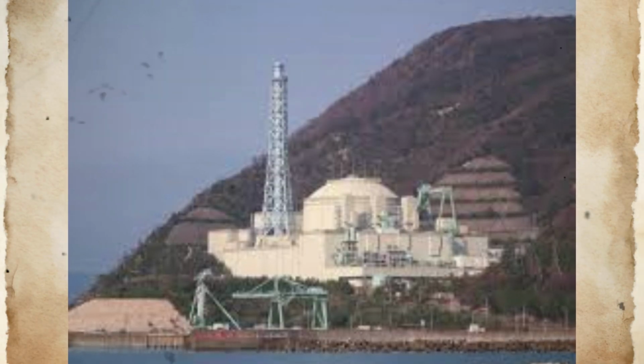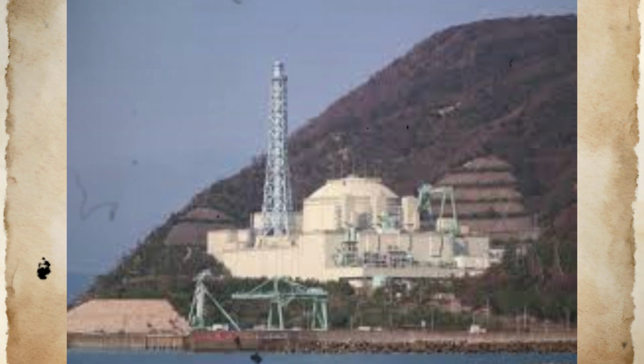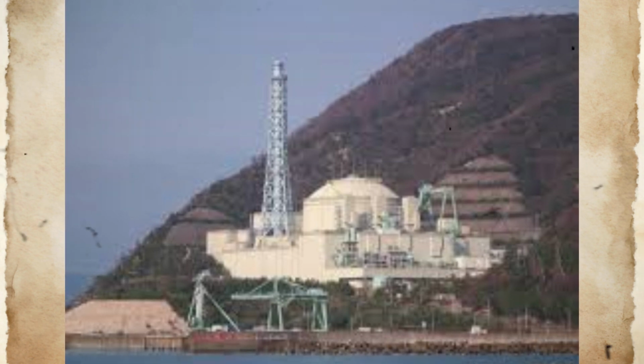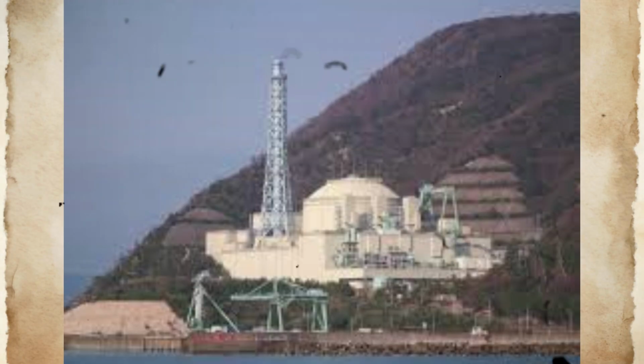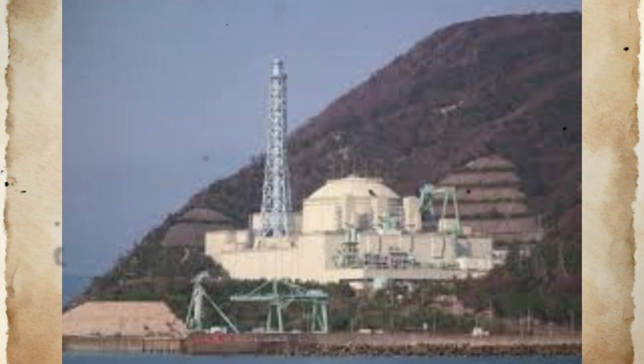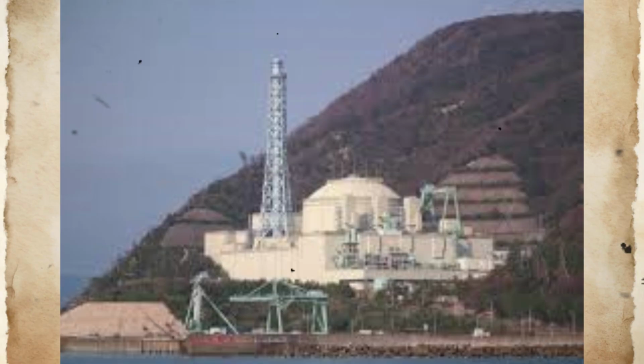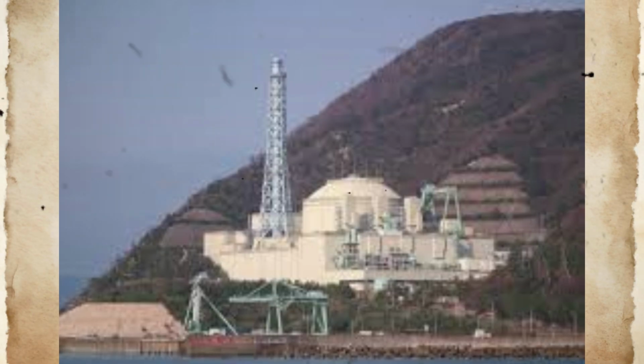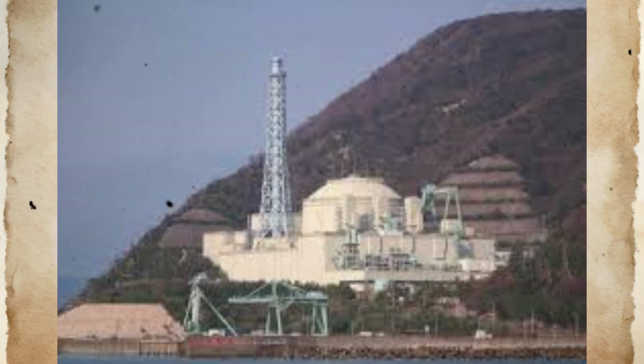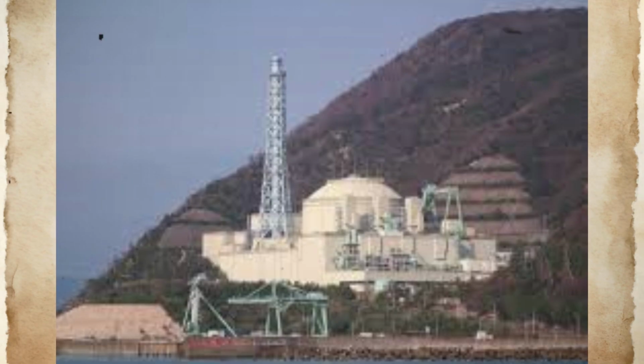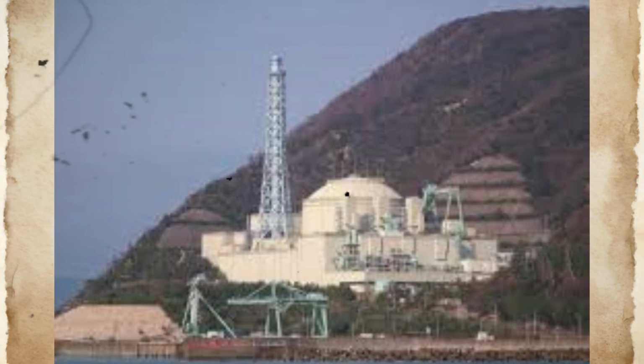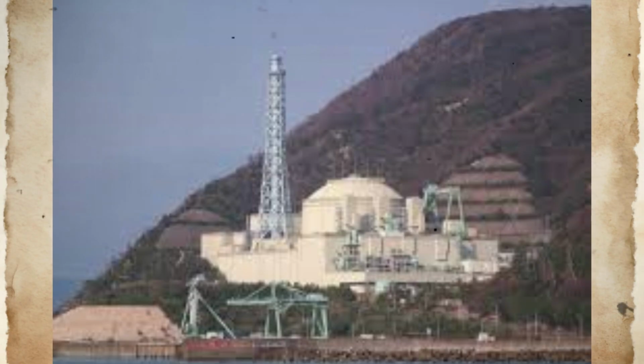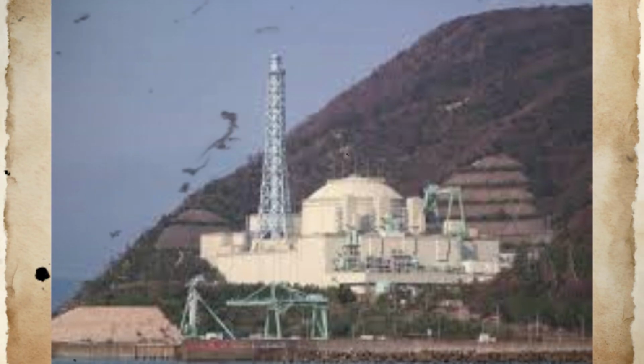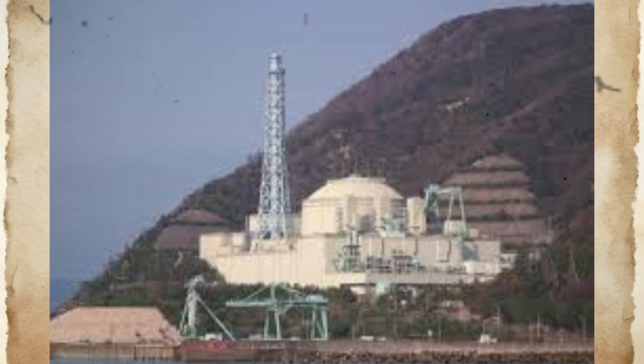Computational fluid dynamics analysis conducted during the post-incident investigation revealed that sodium escaping through the fractured thermocouple well was ejected with sufficient velocity to distribute throughout the piping room. The high-temperature sodium immediately began oxidizing upon contact with atmospheric oxygen and moisture, creating the exothermic chemical reactions that generated heat, light, and gaseous products detected by the fire protection systems.